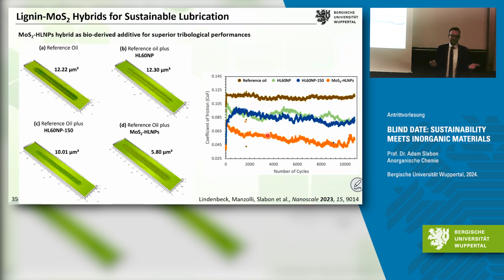But you also have to make the scratch test. So you take basically one metal element, you add the lubricant, and then you go 10,000 times and you see how much wear you have of the surface, which you can then visualize.